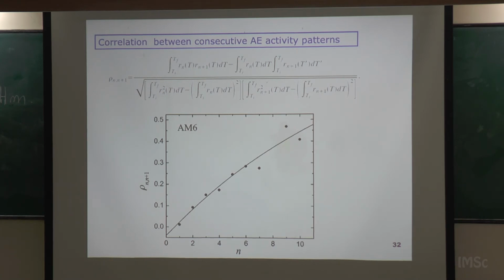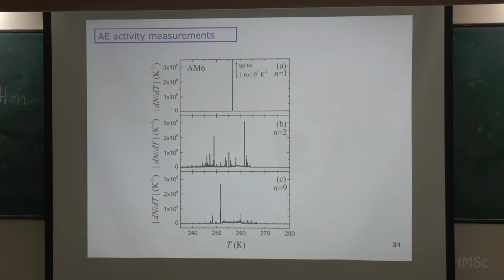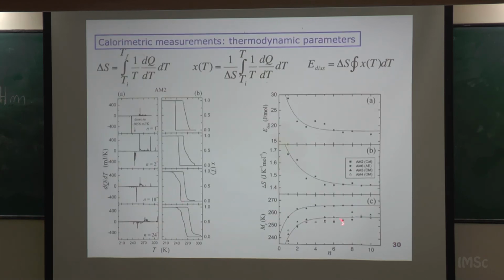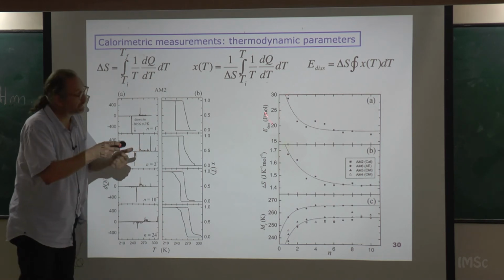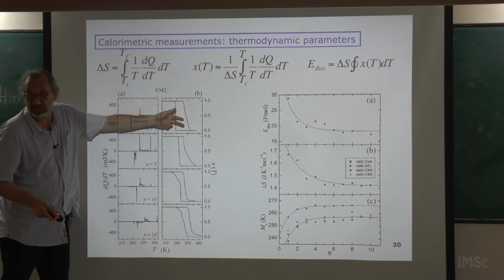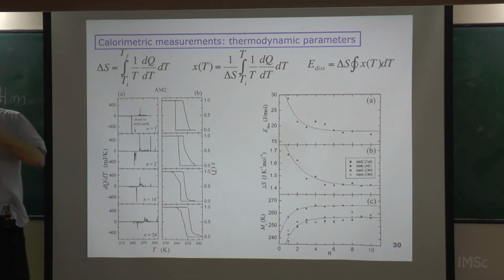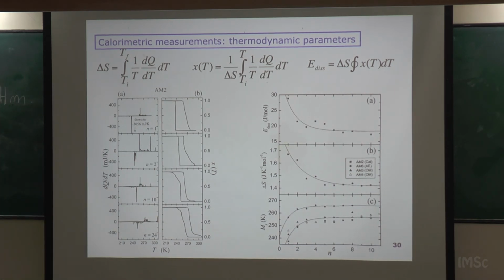And with this learning process, if you go to the hysteresis loop, you can see that the dissipation of energy is decreasing. So the area here is much larger than the area here. So the system is trying to find the best way to transform in order to dissipate less energy. And for that, what is the system able to do? Change a little bit the disorder. The system is relocating the vacancies, is relocating the dislocations so that this proceeds with less dissipation.